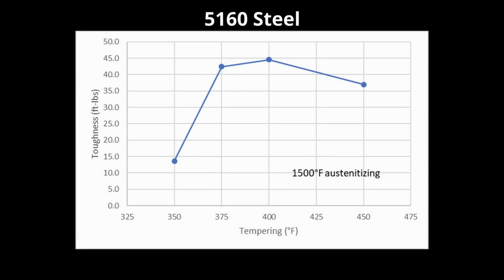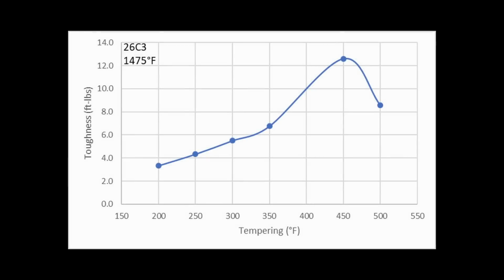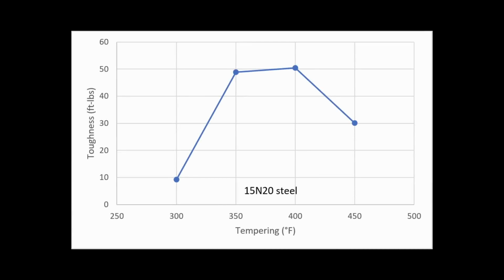We've also seen this phenomenon with other steels at similar temperatures, like 5160, we also saw a drop by tempering at 450 degrees. And 15N20 also saw a large increase in toughness by tempering hotter than 300. Even with 5160, we had to temper at 375 before we saw the big jump in toughness. Some steels behave differently. Some steels you just temper lower and the toughness gradually decreases. But with these high toughness steels like 5160 and 15N20, they seem to have this huge jump above some minimum temperature. So that's something to keep in mind if this is a steel you will be heat treating.